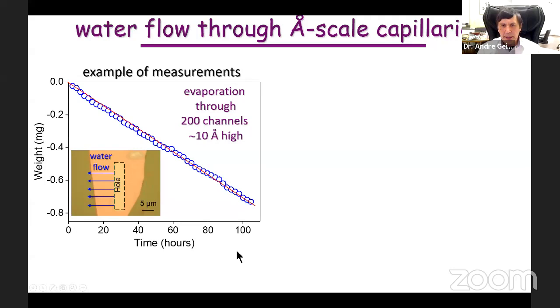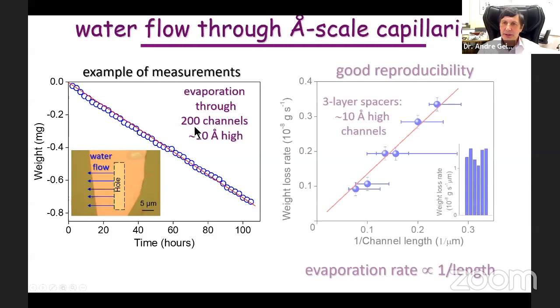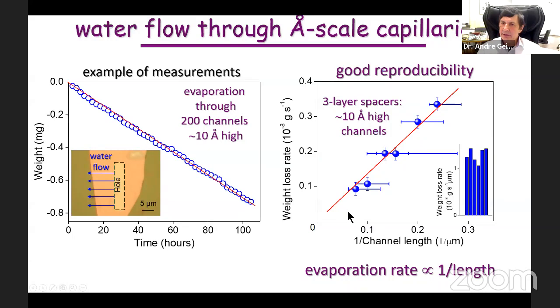We looked over many days at how water is lost from the container, because water flows from it and evaporates on the other side. In this case, we have three-layer graphene spacers, 1 nanometer channels, 200 channels in parallel. And we make channels of different lengths and see what you expect: the longer the channel, the slower the evaporation is. It's quite good reproducibility, which tells us that everything we are doing is quite reasonable.